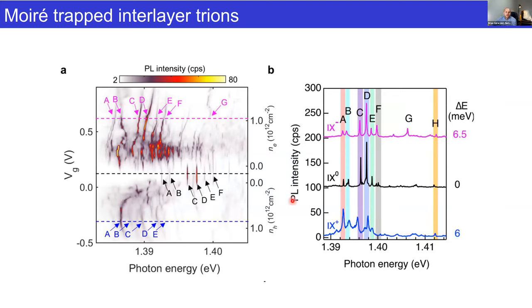And I'll just go very briefly over this. If we zoom in on the spectra, we have our neutral excitons shown here, which we've labeled A, B, C, D, E, F. Then at a certain point, we have the on-site trions formed. Then we have what looks like a lot of noise, and then everything quiets down again. We're left with the same emitters, so we can determine by positions that they are identical. And if we shift the line cuts of these energies at the positive and negative bias, we see that these really are the same, with the same emission energy, just with the additional Coulomb interaction. In this case, we've shifted the n-doped by 6.5 meV and the p-doped by 6 meV, and we end up with very good agreement.